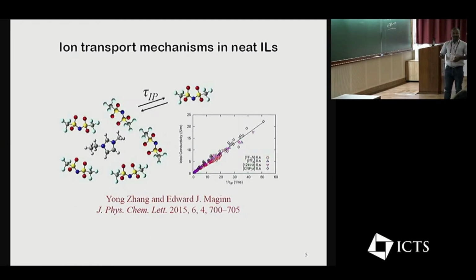In the electrolytes community in 2015, Maginn and co-workers studied a series of liquid electrolytes and showed this non-Einstein conductivity, where the diffusion coefficient is directly proportional to the conductivity. So the ionic conductivity is proportional to one of the underlying relaxation phenomena. Here it is the ion pair relaxation time scale. You can notice the inverse scaling, with 1 over tau IP on the x-axis.